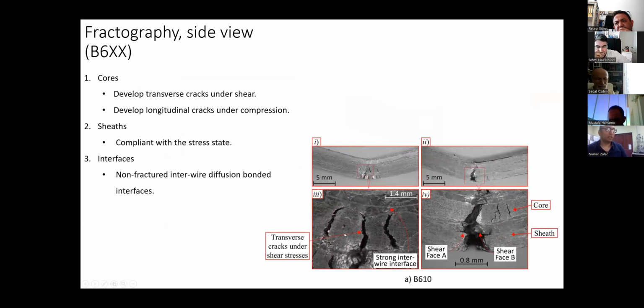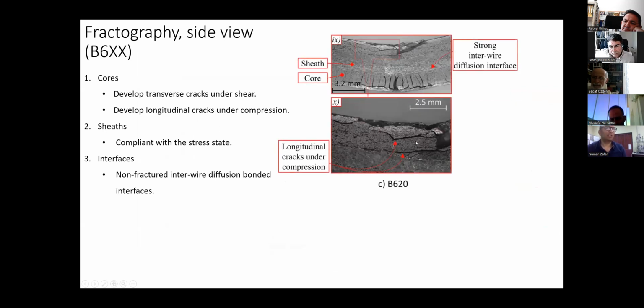Here also transverse cracks in the core, and the sheath's shear face A and shear face B show that this is an interwire boundary, where longitudinal cracks are formed in the sheaths. Same thing, but I want to say that the compressive stresses result in the longitudinal cracks in the core, in the top layers. Again, longitudinal cracks are seen in the cores only when they are subjected to the compressive stresses. Under tension and shear, here and here, they always develop transverse cracks. But I want to draw your attention to this region. This is an interwire boundary region, which does not have any cracks.